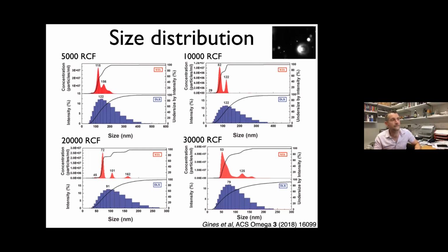But this movie kind of illustrates what's going on, because you see this particle here, right? This is a bit big and it's flaring, right? So in the DLS, this would be dominating the spectrum. But in NTA, we can see the other stuff at the same time. So there are advantages to that. But anyway, if you play all these games and centrifuge super fast, you get down to about 50 nanometers, something like that. So you can go quicker than this. This is not particularly fast on a centrifuge, actually.